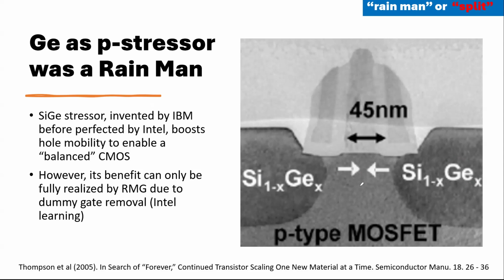Stress here is about 1 to 2 gigapascal. By the way, you need to have a dummy gate removal, right? Which means initially when you do the source and drain growth, eSiGe, you don't get this strain. You have to remove the polysilicon and put your high-K in. When you remove it, things relax here. When you relax, that's where this happens.